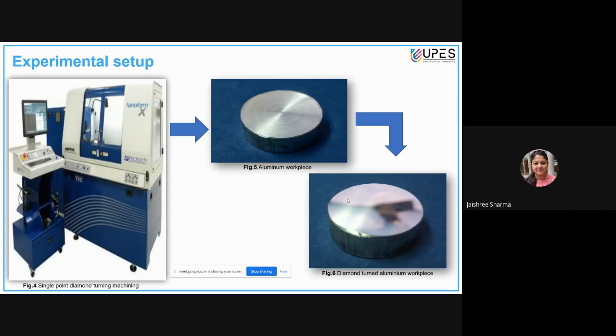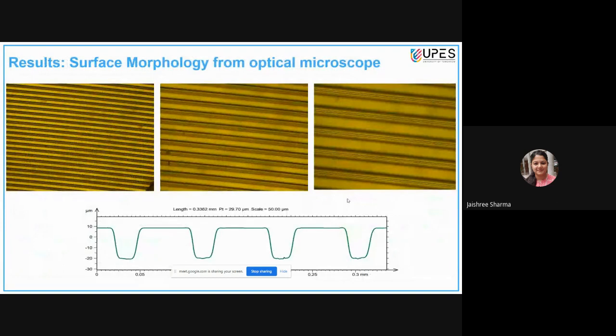Also, super hydrophobic coatings are well known in society and in different industries due to their self-cleaning characteristics. These coatings are used in multiple sectors, including marine, automotive, optical devices, textiles, etc. Super hydrophobic surfaces have attracted a lot of attention for their wonderful uses, but practical applications in the optical industries are restricted because achieving super hydrophobicity and transparency at the same time is a technical challenge. To overcome this difficulty, one of the most promising techniques available today is single point diamond turning machining, which can produce hierarchical micro nano structures with extremely smooth surfaces and roughness within a few nanometers.